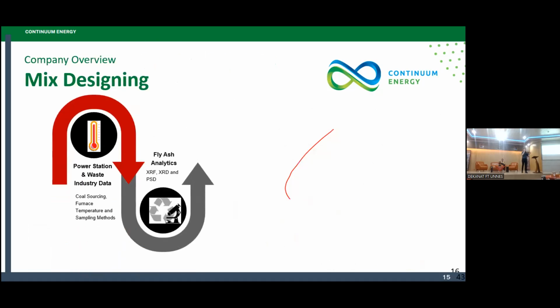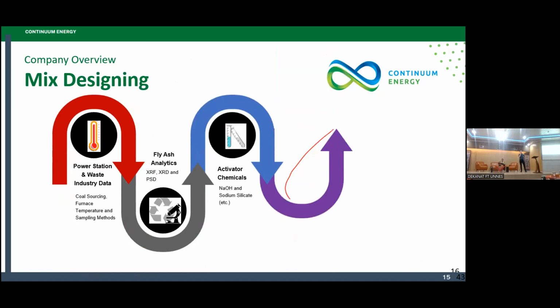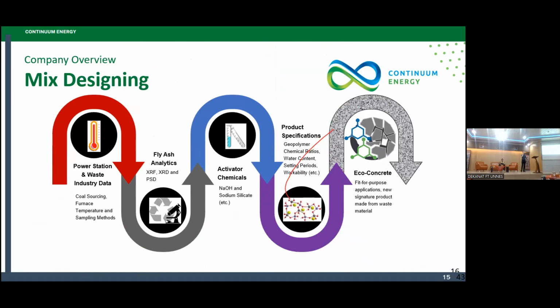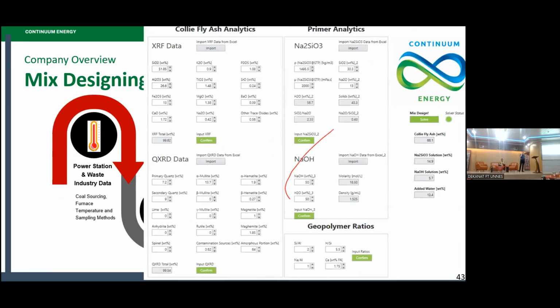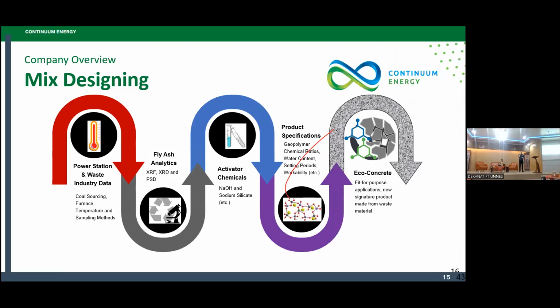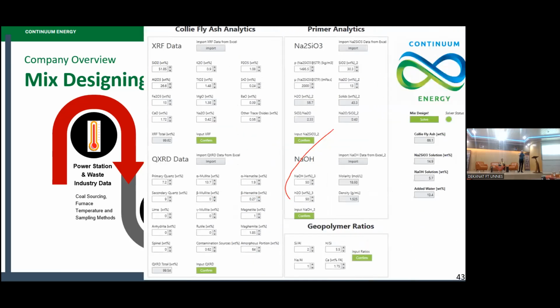And essentially, when it comes to actually making this geopolymer, there are various steps. We first have to analyze the waste, whether it's from a power station, coal plant, or the red mud from the aluminium industry. There's a lot of information on waste and how we can deal with it. And then from that, we do testing on it, X-ray fluorescence, X-ray diffraction. Then we do testing on the chemicals we use, the small amount of chemicals. And then we also analyze it and make a fit-for-purpose concrete that can be made into products. Next slide. So this is pretty much just showing the process we use. It's a very complex process, but it can make any concrete material that you like, incorporating a lot of waste.